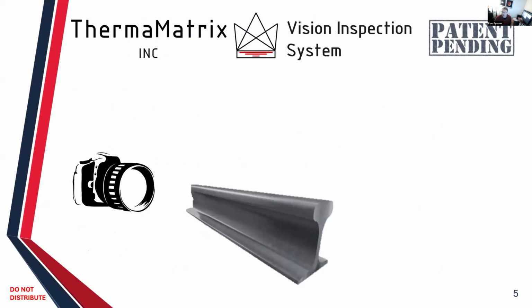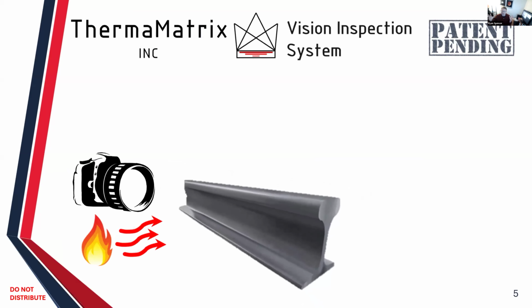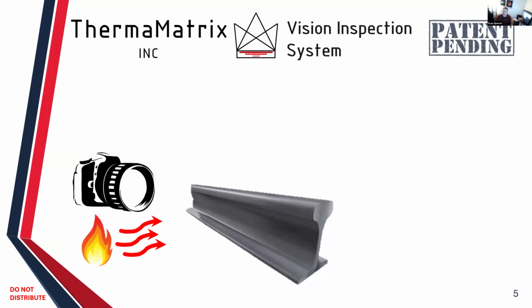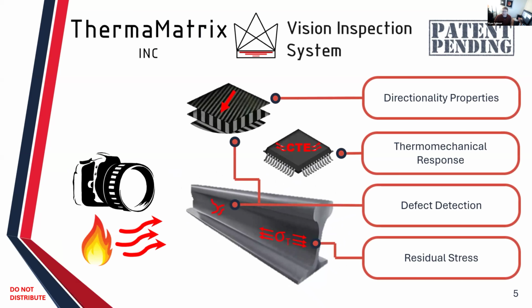So what differentiates our technology from ordinary vision inspection systems? Traditionally, you have camera systems, and they just take a snapshot of what's occurring right now. I call this a static image. Usually this is defined for dimensional analysis or maybe surface inspection. Where ThermaMatrix comes in, we introduce a heating methodology, and we monitor the thermal expansion and contraction of that material. Now, rather than just dimensional analysis and surface inspection, we have a multitude of capabilities through thickness, understanding of your material, and we can provide these main capabilities: directionality of your material properties, thermomechanical response, overall defect detection, and we're trying to crack the code on residual stress monitoring also.